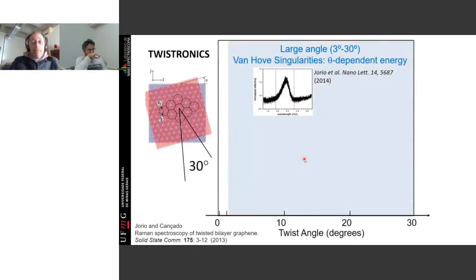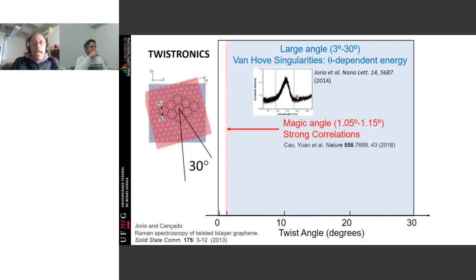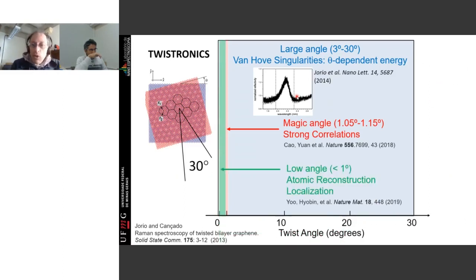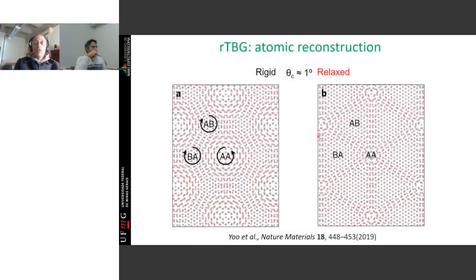All right, let's summarize. If I rotate graphene, the hexagon, between 0 and 30 degrees you have all the possible situations. If you go over 30, it repeats back, okay? So rotating from 30 down to almost 1 degree, you have many properties that depend on the angle, like the optical absorption. At exactly 1.1 degrees, you have the magic angle, strong correlation, and superconductivity. And below this angle, you have atomic reconstruction. So these are a plethora of things that happen with the twisted bilayer. All right, so I remind you of these structures, and now we want to look at this optically.